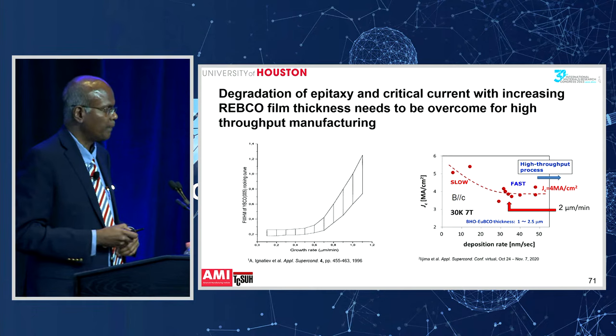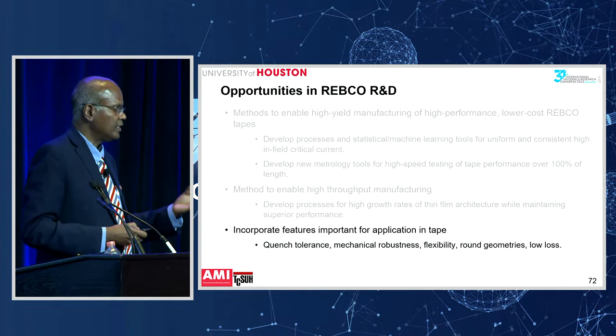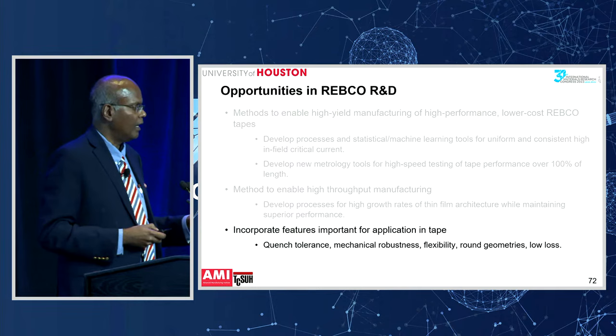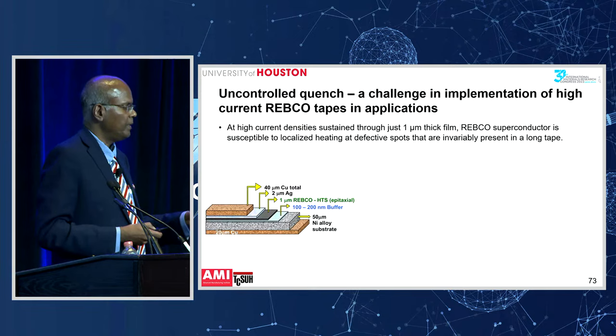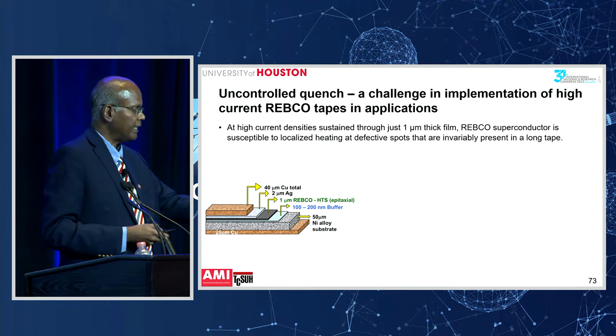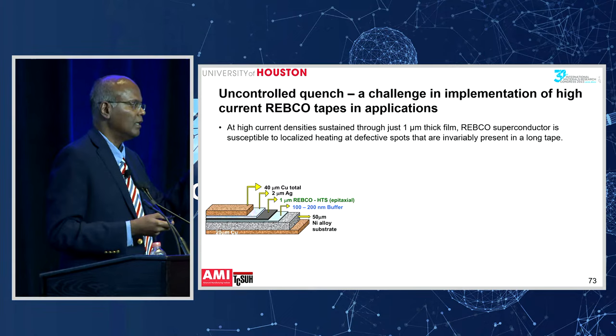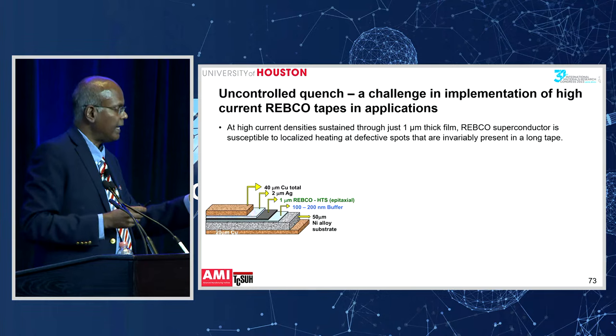The last topic here is that our opportunity is to incorporate features which are important for applications, right? I didn't really cover much of that today, but there are a few things which are important for applications. One is something called quench, and let me just quickly explain that in this slide. What happens is the superconductor carries so much current. That tape I'm showing right there can carry 500 amperes, over a very small cross-section. If there's any defect, and you're trying to make a kilometer-long tape, if there's one defect, that can be a source of hotspot. That can start heating up.